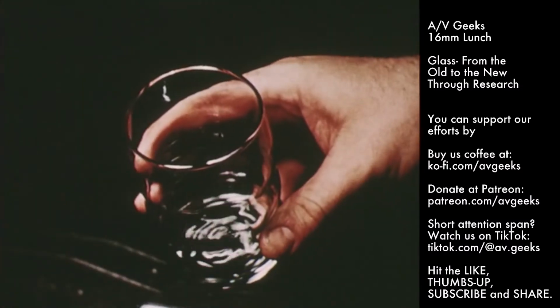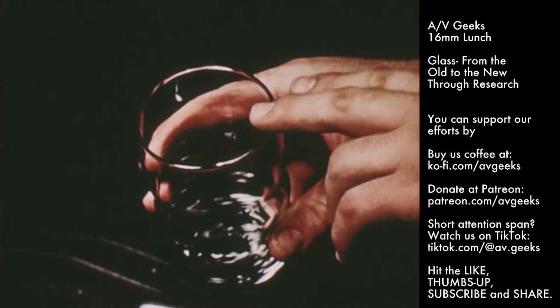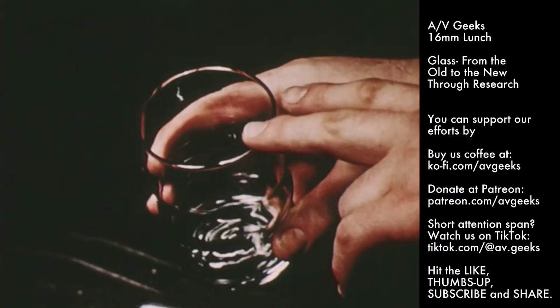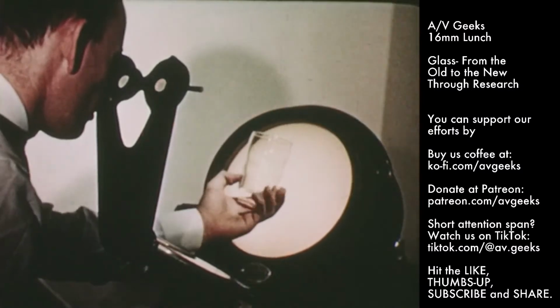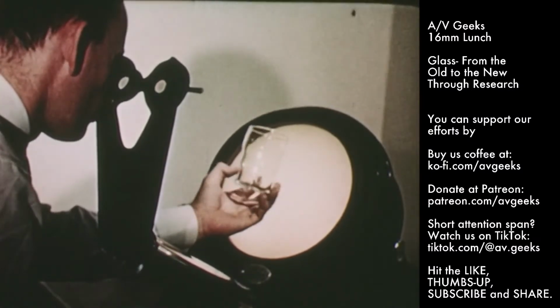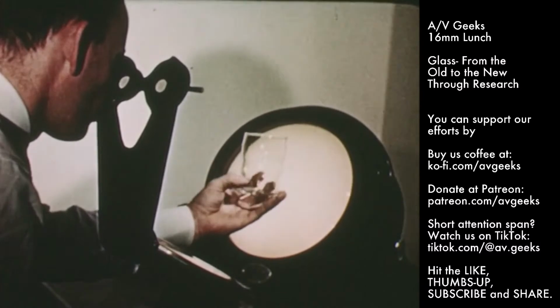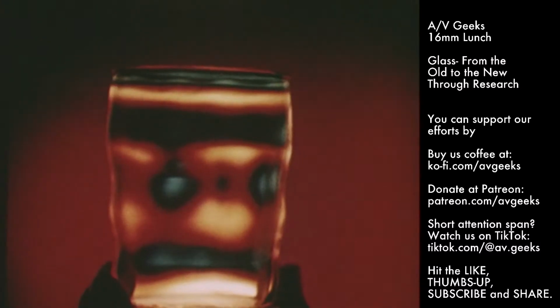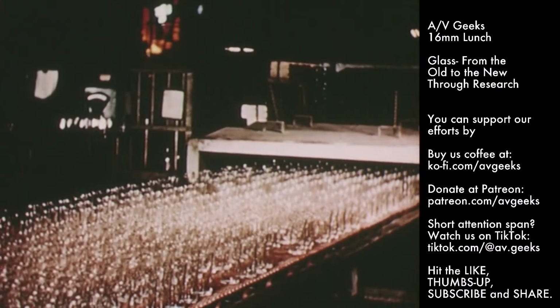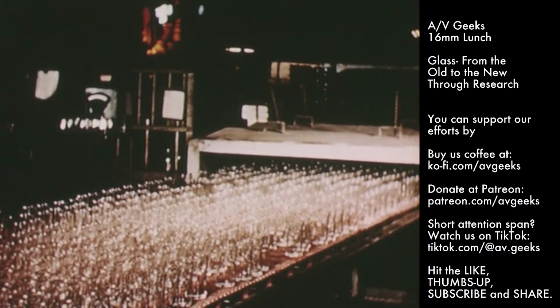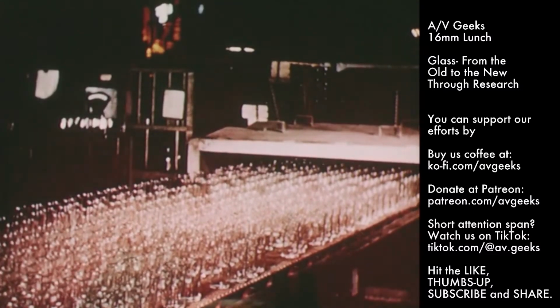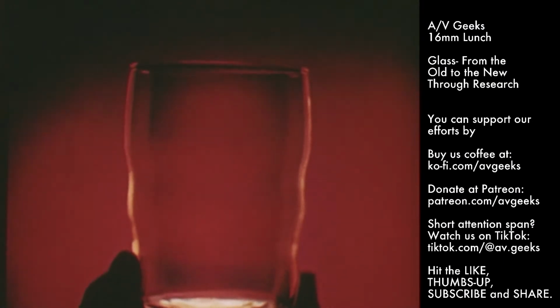For example, here's a tumbler. It looks perfect, but let's test it. One successful test that has been devised employs polarized light. Look for strains in the glass. They show up as dark areas. Undesirable strains could lead to early breakage. But when the tumblers are annealed by slow cooling, these strains disappear. This superior product is the result of experimental work.